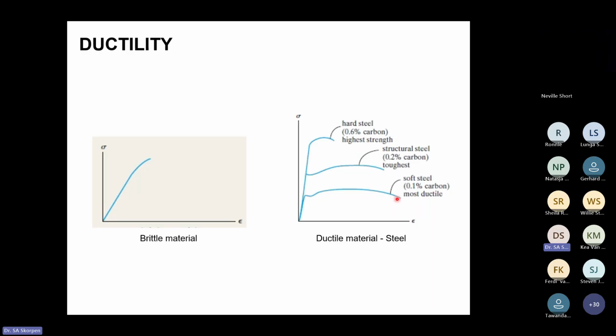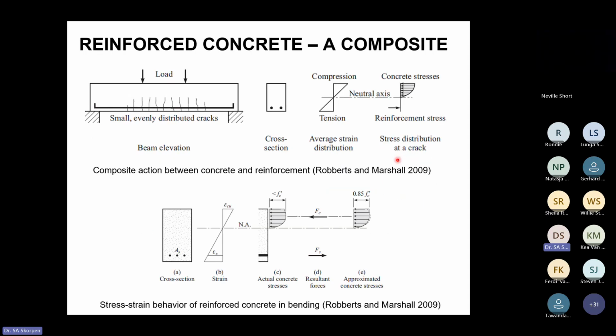So ductility is basically a measure of the strain deformation that a material can undergo before you get final fracture. What one needs to watch out for in structural steel is that as you tweak the strength of the steel, and typically that's done by adding carbon, you're increasing the amount of stress that it can handle, but you're decreasing the ductility, the amount of strain that happens before you get fracture. So that is our definition of ductility, and it's important to keep that in mind when we are looking at the design for flexure.